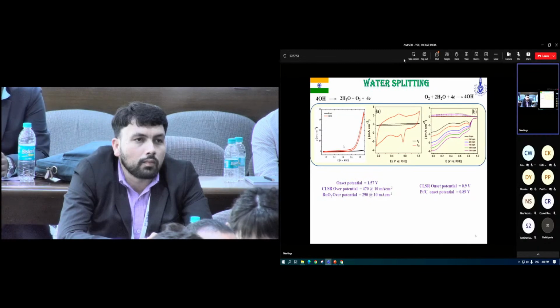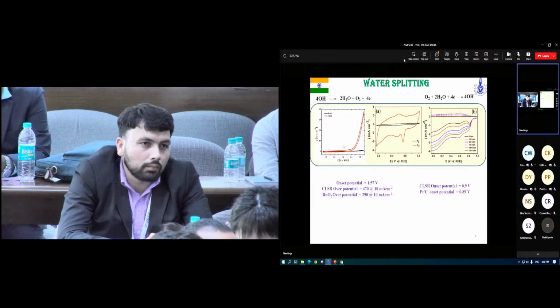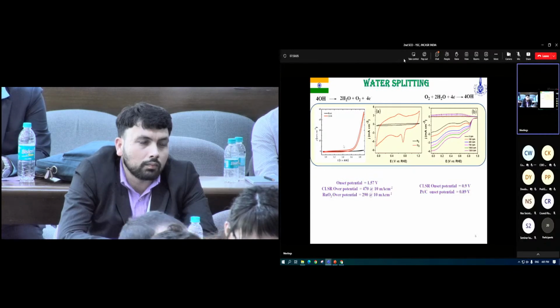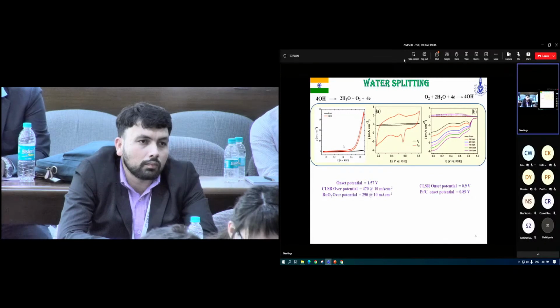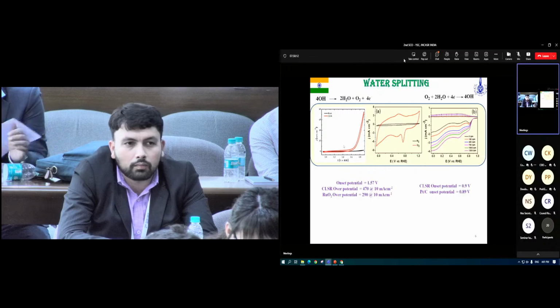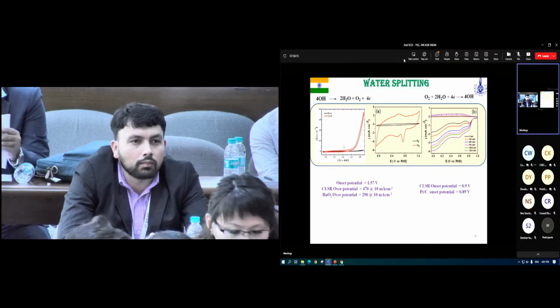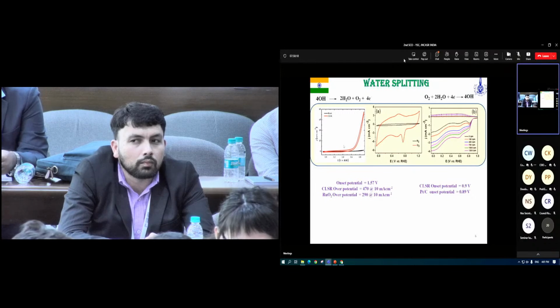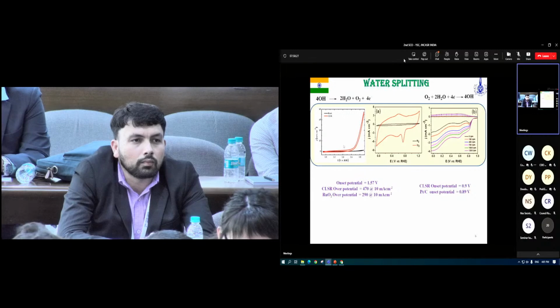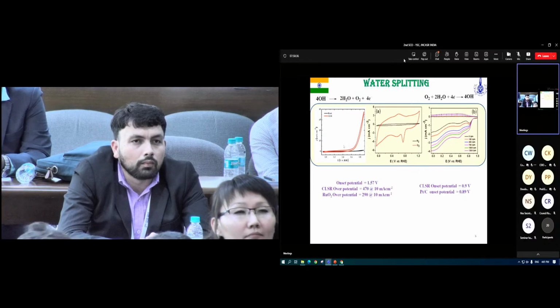Here we can see the oxygen evolution reaction, where oxides are converted into oxygen by the 4 electron pathway. And on the second side, this is the oxygen reduction reaction, which is a half cell reaction for fuel cell applications. For that CLSR material, when we compare our data with already reported materials, we found a very good onset potential for ORR activity, 0.9 volt, which is very equivalent to the benchmark platinum on carbon catalyst, and very good data for the OER catalyst. The benchmark is RuO2, but the stability of our material is higher compared to RuO2.